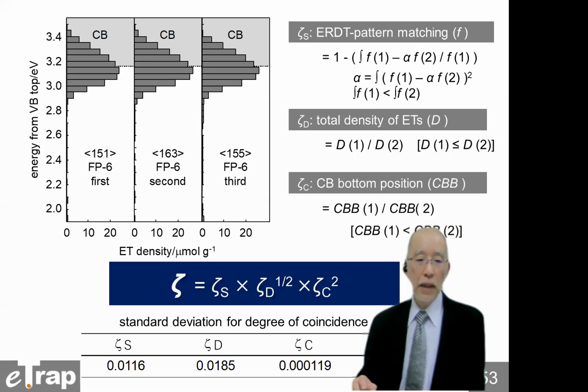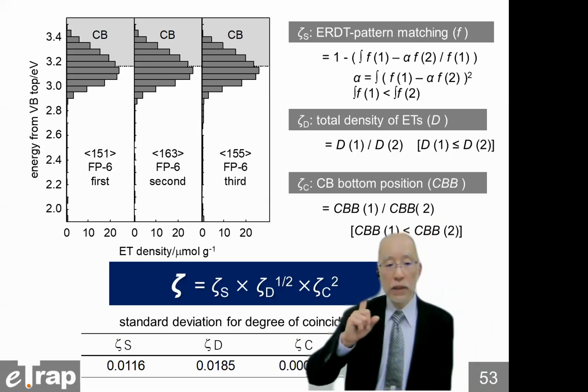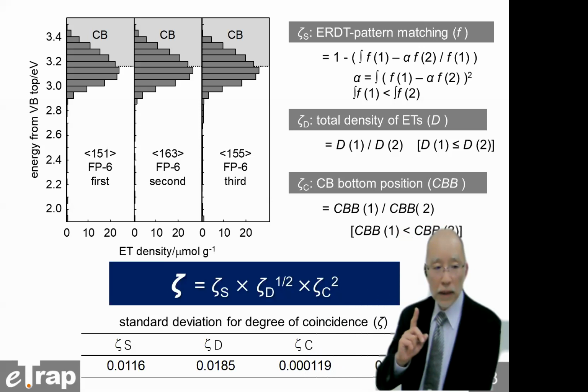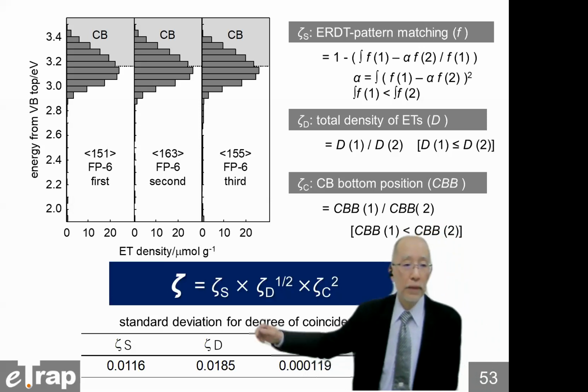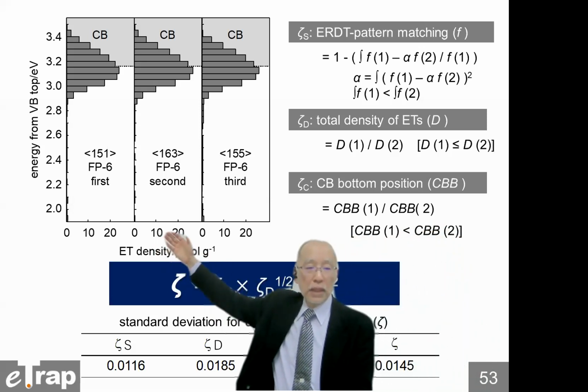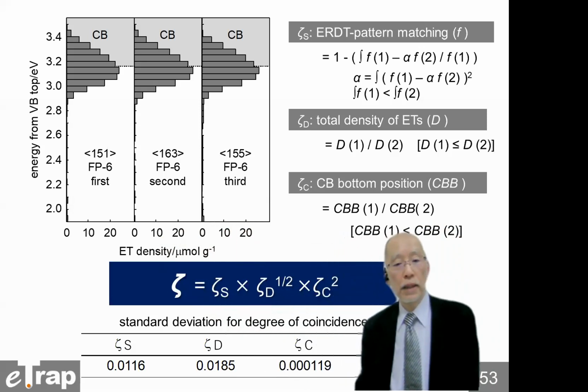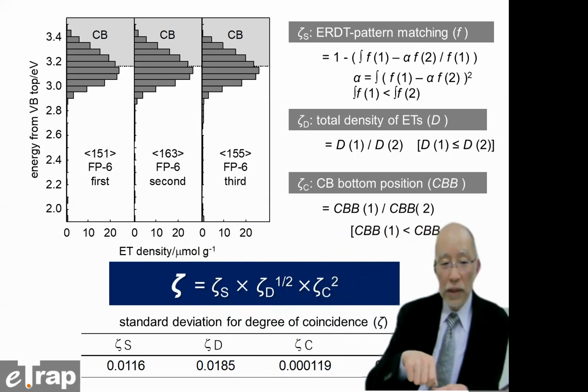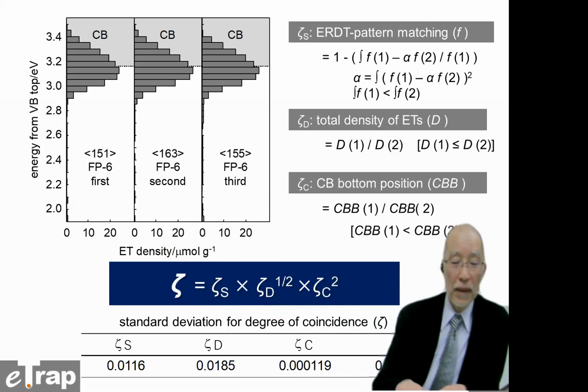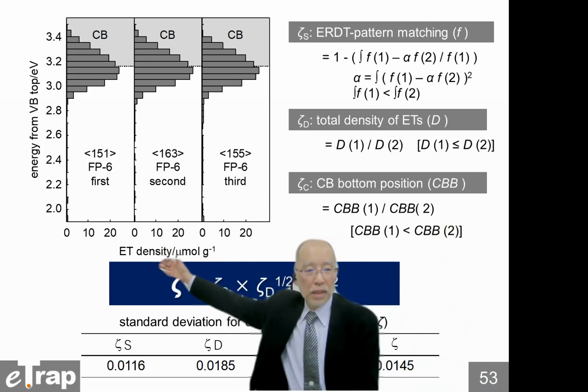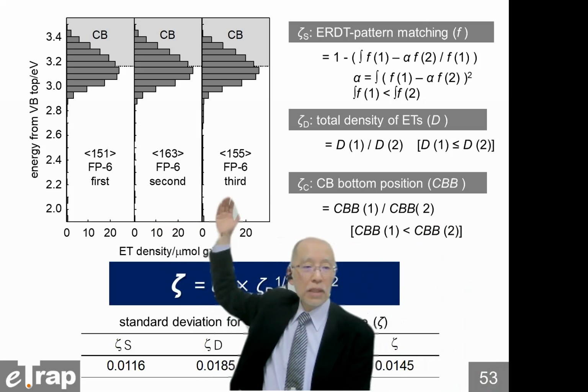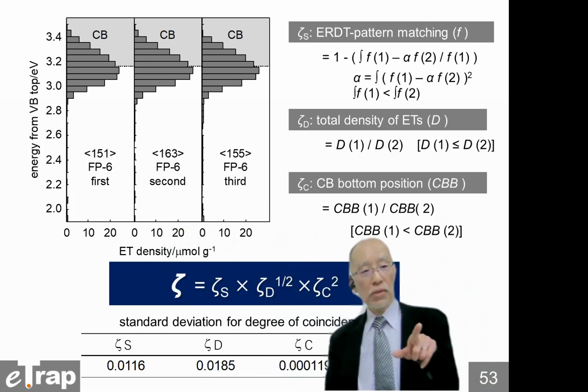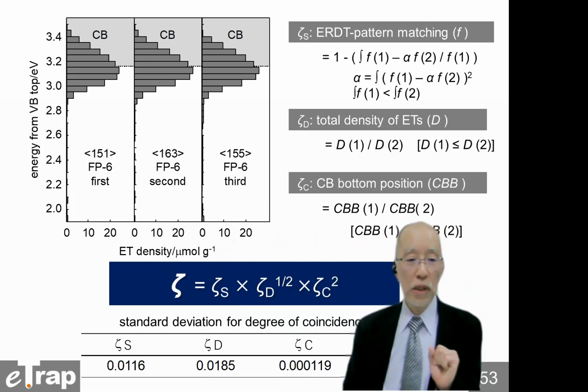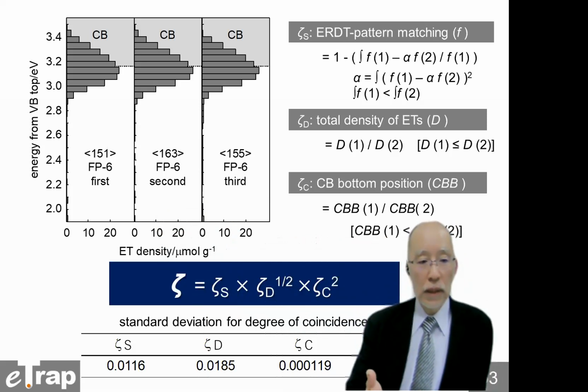And then we selected one commercial titanium oxide, anatase titanium oxide, FP6, provided by Showa Denko, and we measured the ERDT/CBB pattern of samples taken from the same bottle, from almost the same position in the bottle. And we could measure almost similar patterns. By seeing this, you can see they are almost the same, but we need to analyze quantitatively.